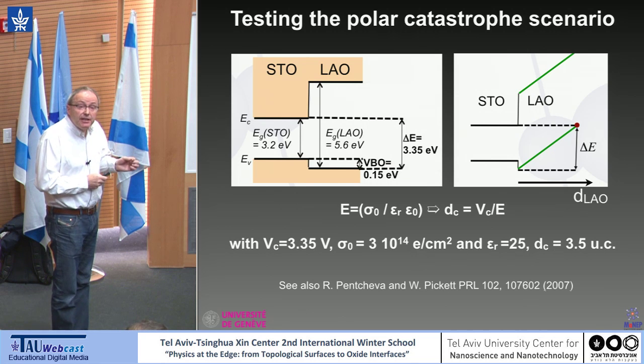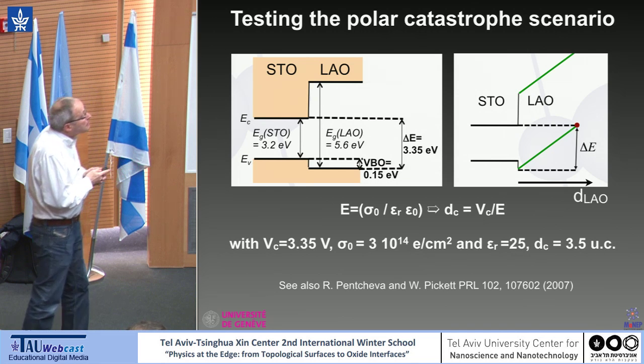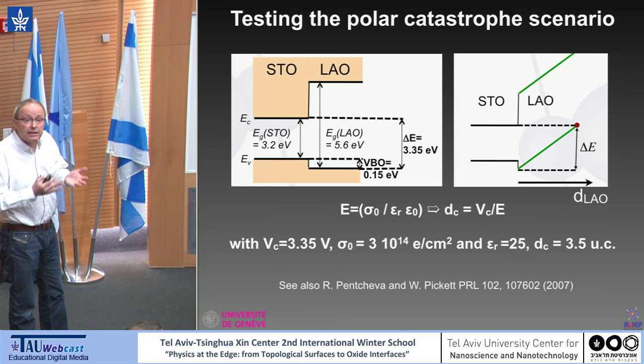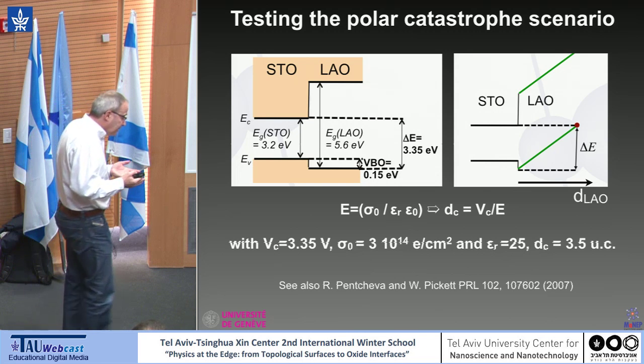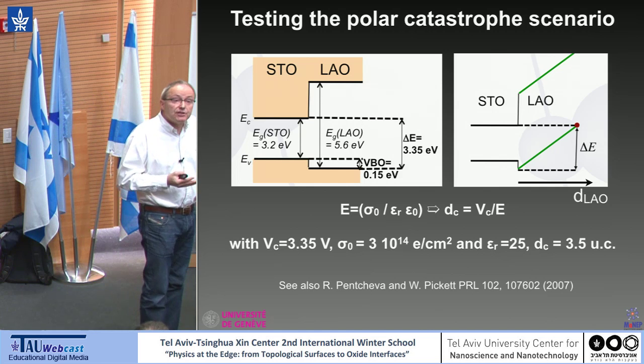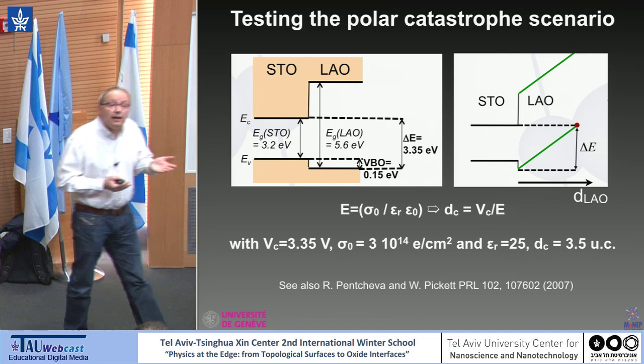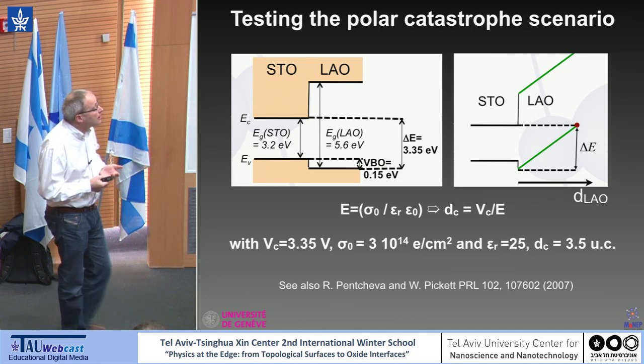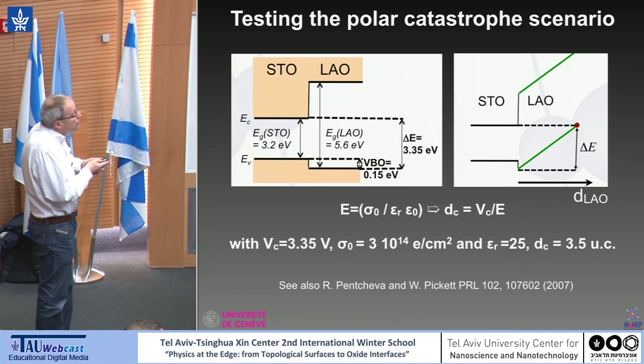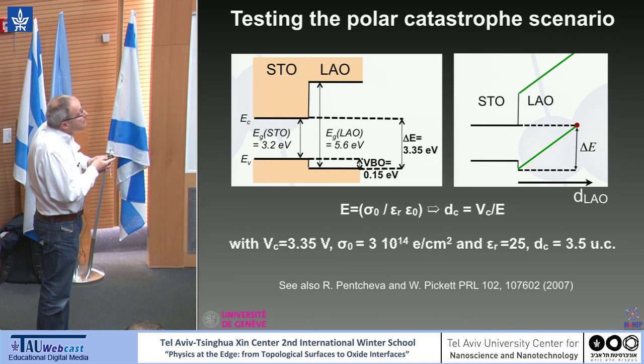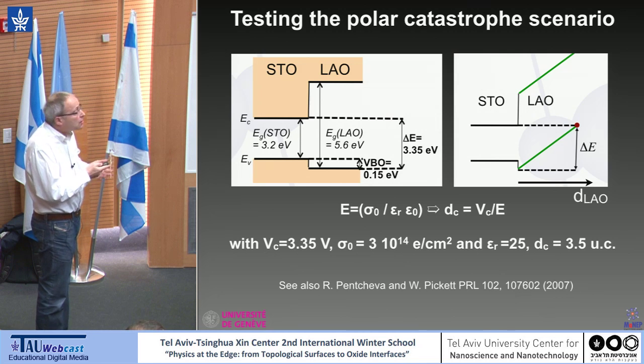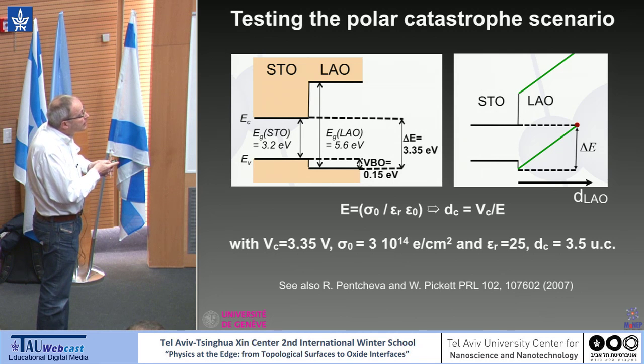It is very easy to calculate this critical thickness, because we know the surface charge. You know that in a capacitor, the electric field is simply the surface charge divided by the dielectric constant of the material and the vacuum dielectric constant. So you can calculate the electric field. We know this distance in energy or in volt, and so you can calculate the critical thickness.